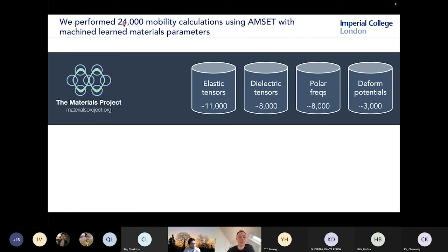Now, as I mentioned before, in AMSET we need common materials parameters, things like elastic tensors, in order to calculate scattering. Unfortunately, we don't have all of these materials parameters available for this many materials. So I trained machine learning models to predict these materials parameters. I took the elastic tensors, dielectric tensors, and phonon frequencies from the Materials Project, and also calculated 3,000 deformation potentials of my own.